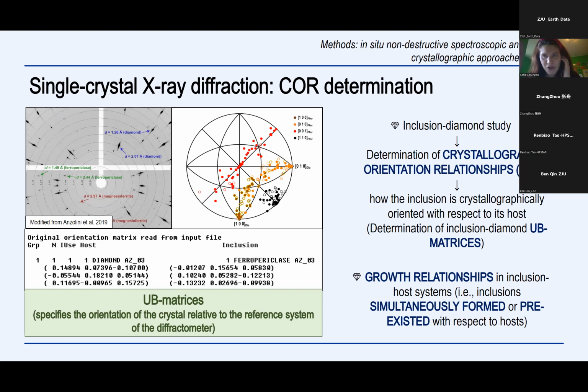This is possible through the determination of the UB matrices of the inclusion and of the diamond. The UB matrix is a parameter that specifies how a mineral is crystallographically oriented with respect to the reference system of the diffractometer. This information is very important because it allows us to understand and determine which kind of growth relationships can exist between inclusions and their diamond hosts, so to determine if inclusions are syngenetic or protogenetic.